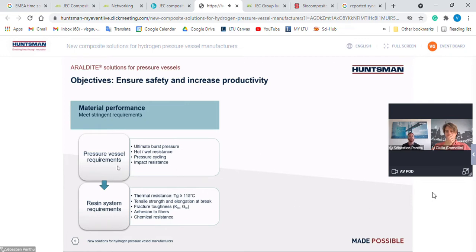And when we translate those to the resin system requirements, we establish a kind of specification chart where we pay attention to the Tg, which should be above 115 in dry conditions. We try to get the highest tensile strength and elongation at break, which will influence the ultimate burst pressure. And then we work on the fracture toughness and adhesion to fiber to maximize the endurance testing and the fatigue resistance, as well as the chemical resistance to protect the fibers against the environment.